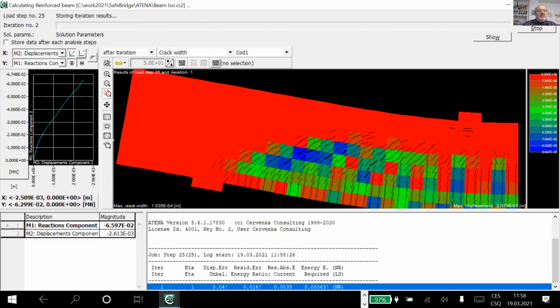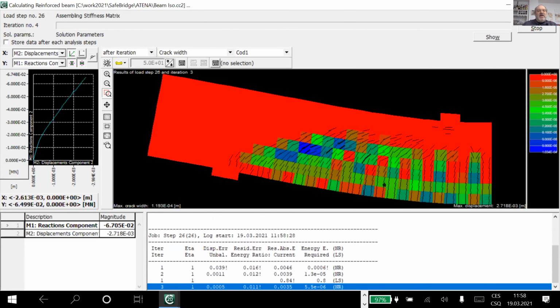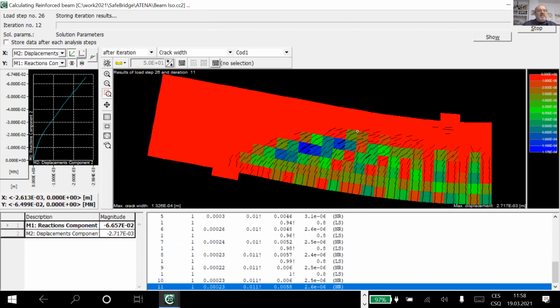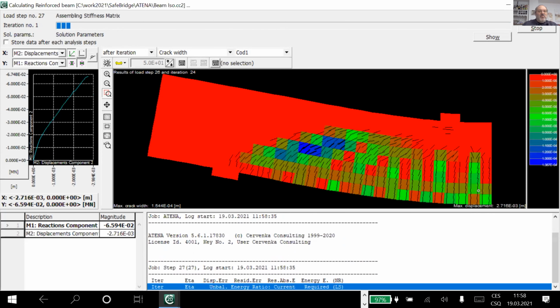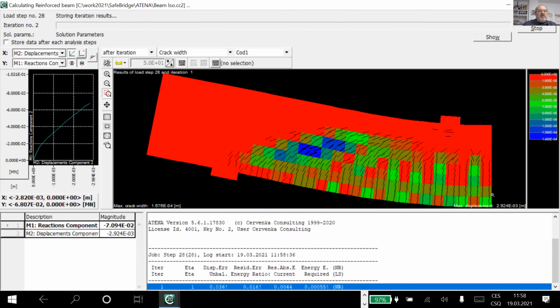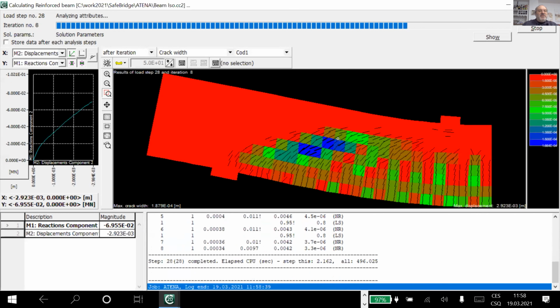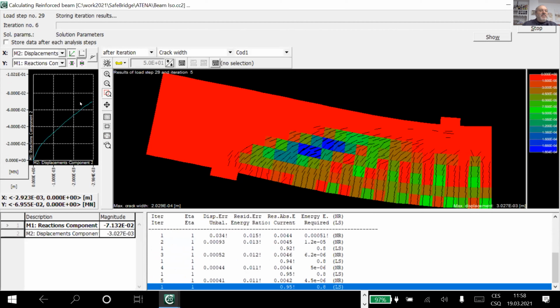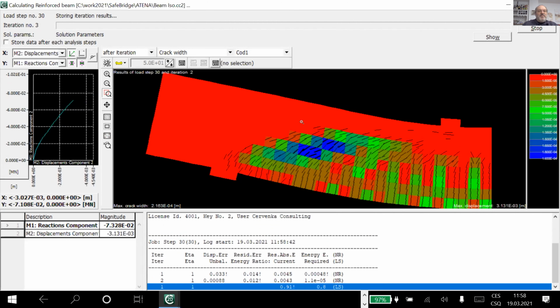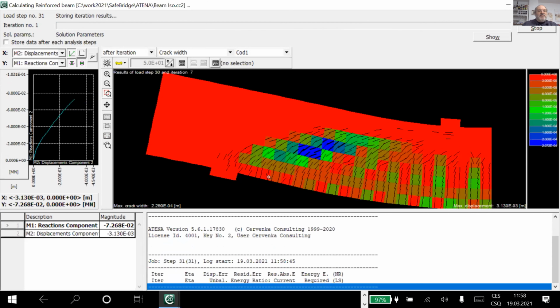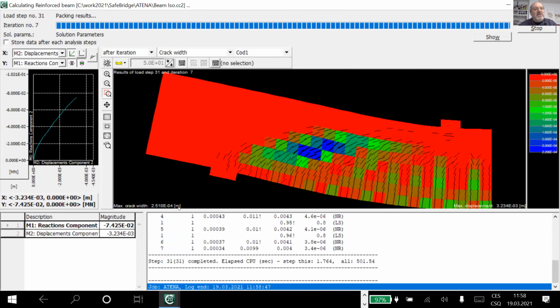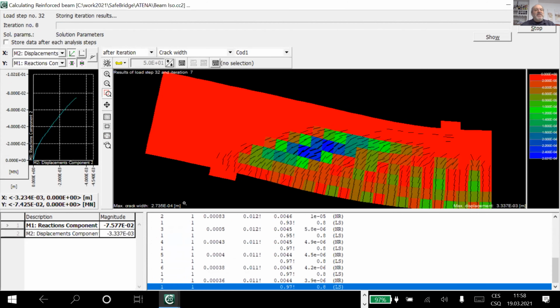Now the original bending cracks are slowly transferred to the shear crack. You see these blue values are moved from the bending region here to the shear region, which is here. And now we are coming slowly to the maximum because these cracks become larger. Now we have already 2 or 3 tenths of a millimeter.